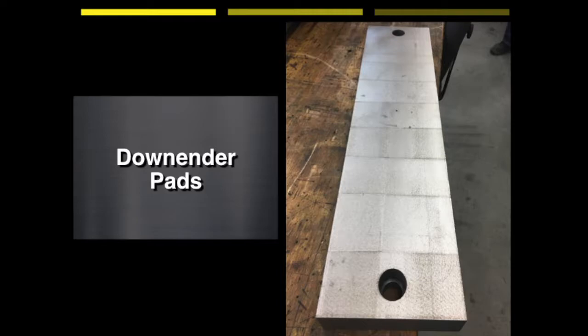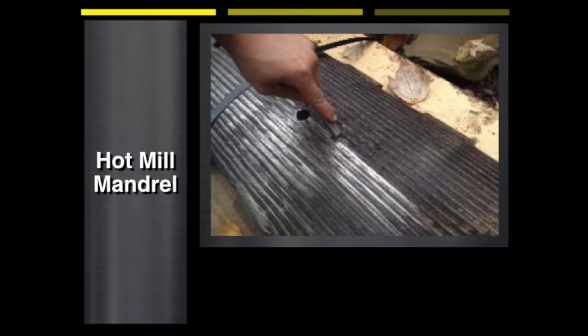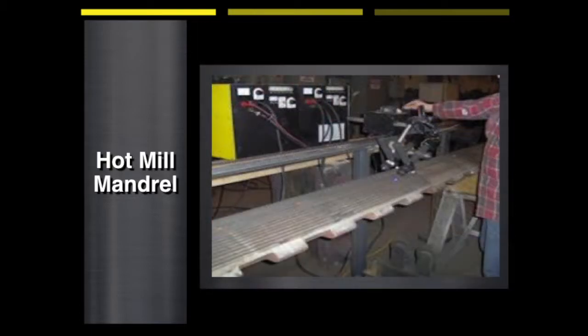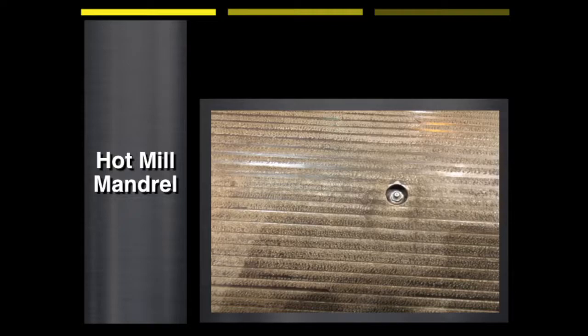The next development in the evolution of this technology takes us to hot mill expanding mandrels. Here we have a worn mandrel that's actually ready for refacing. It takes a good amount of surface preparation to get these cleaned up and remove the galled aluminum from the surface. In this picture, the coating is applied to the worn mandrel using ESD and a robot. And finally, we have the finished product of the coating on the high section of the mandrel face. On this particular mandrel, we're actually able to apply the coating thicker in heavily worn areas to restore the mandrel to a more uniform diameter.